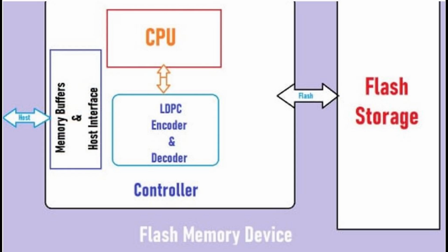When supplied with power and idle, the charge of the transistors holding the data is routinely refreshed by the firmware of the flash storage. The ability to retain data varies among flash storage devices due to differences in firmware, data redundancy, and error correction algorithms. An article from CMU in 2015 states today's flash devices, which do not require flash refresh, have a typical retention age of 1 year at room temperature. And that retention time decreases exponentially with increasing temperature. The phenomenon can be modeled by the Arrhenius equation.